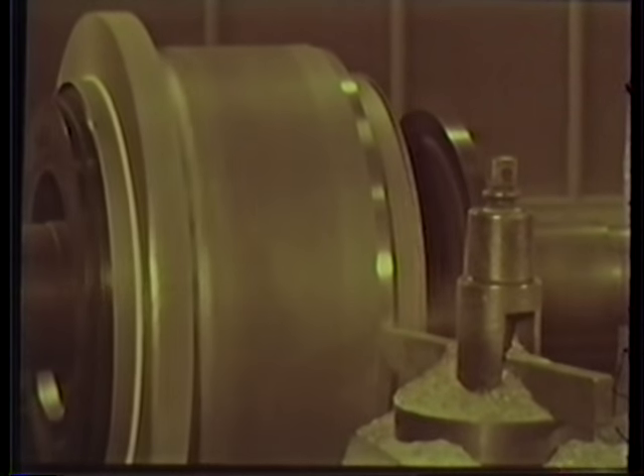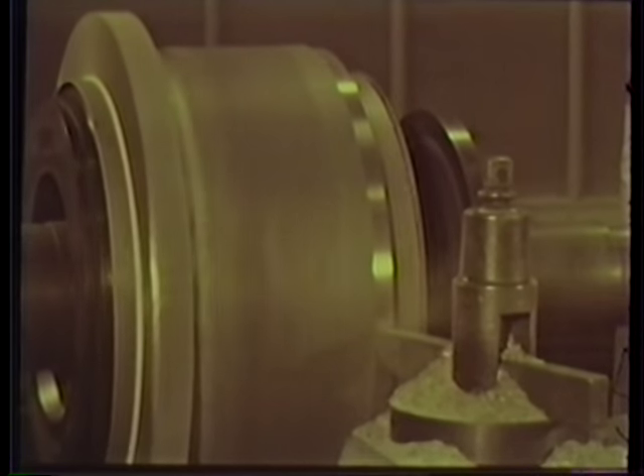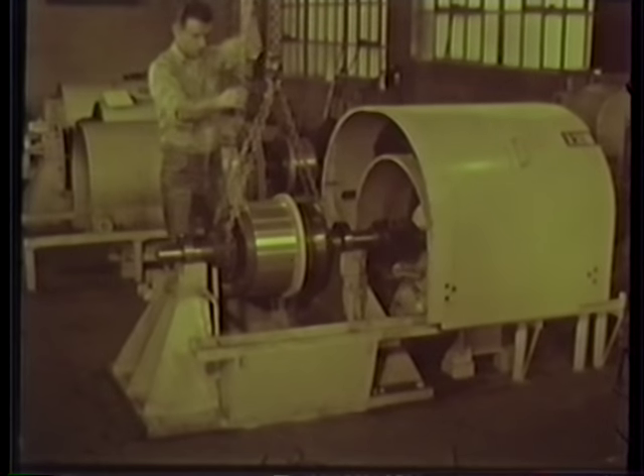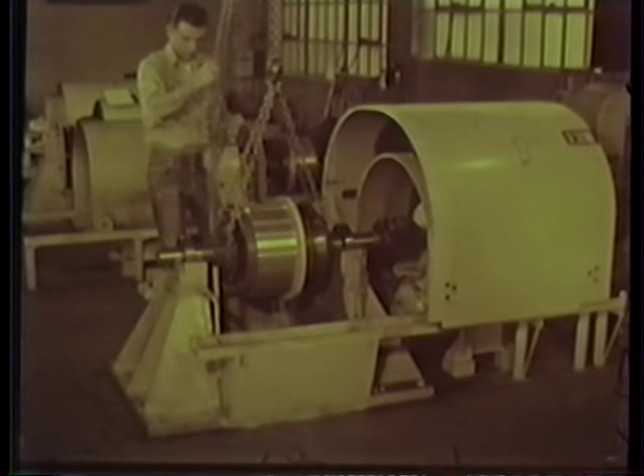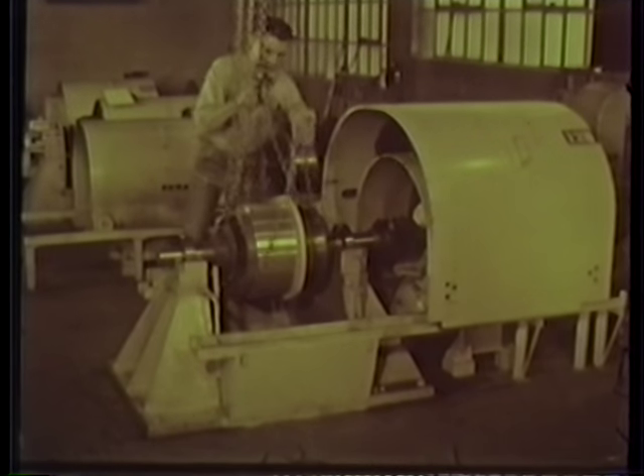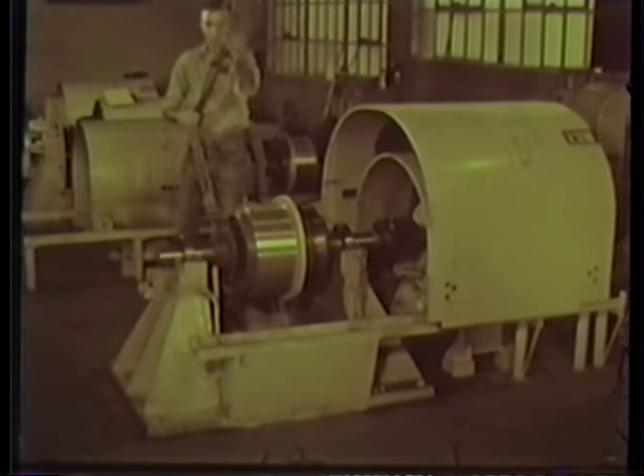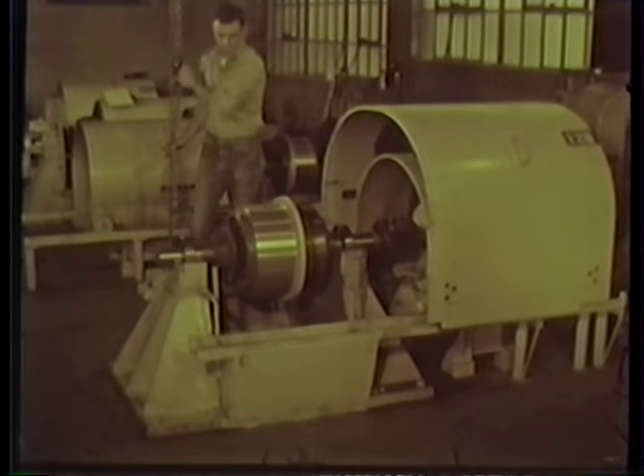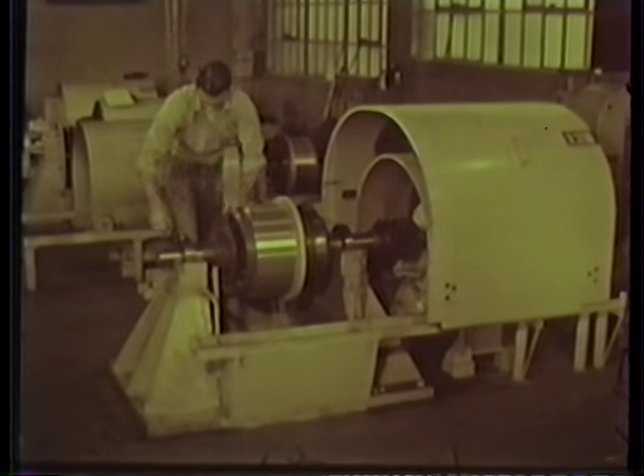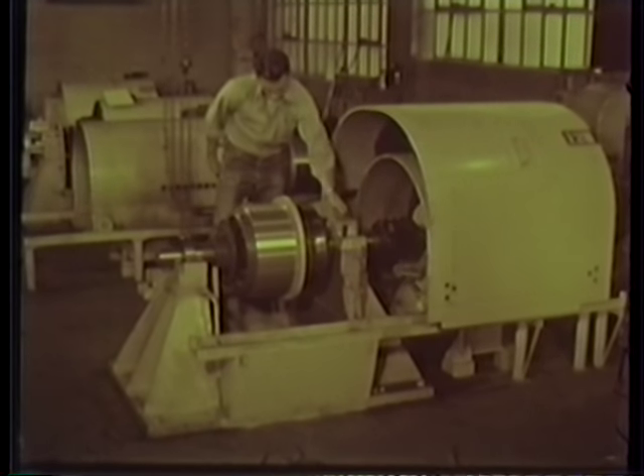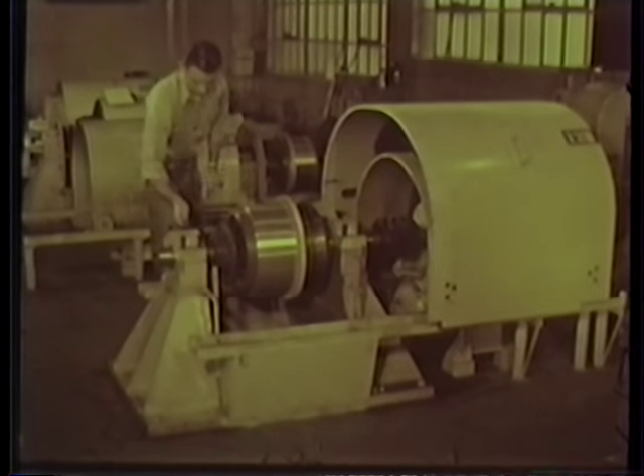Seasoning to obtain stability is now complete, so the brush diameter can be turned. Traction motor commutators receive an additional processing step, known as spin seasoning, to assure smooth operation. In spite of a thorough pressing and baking cycle, the tremendous centrifugal forces and temperature extremes encountered in unusual service may cause the segments to readjust themselves, resulting in a rough commutator. This series of high-speed spinning cycles under heat is one of those additional precautions taken to assure no in-service trouble after the commutators are installed on the armature shaft.